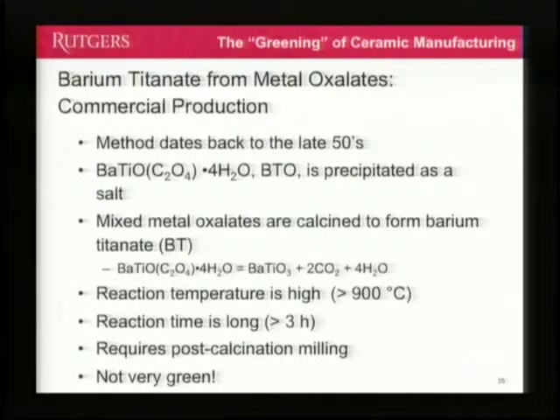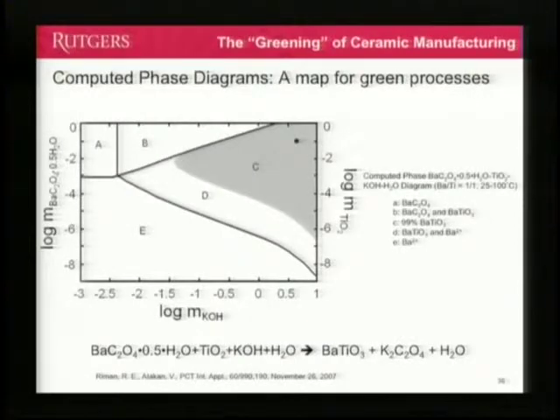So an oxalate is actually two CO molecules joined at the hip, so to speak. And these metal oxalates are calcined. So for every mole of barium titanate, you get 2 moles of CO2. You usually have to heat this above 900 degrees C. The reaction time is at least 3 hours. You have to mill it. It's not very green. So one of the things that Vahid said to himself is, well, gee, what if I look at a way of doing it in water?